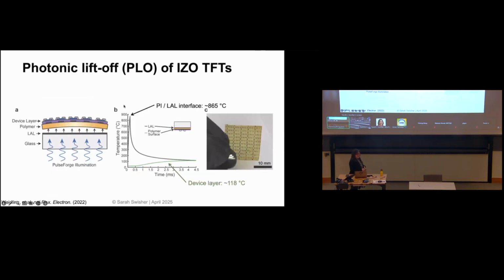So if we look at this lift-off device, what we see is that here's the temperature right at that interface. And if you look as a function of time, it rapidly drops, and here's the device layer heating up a little bit on the back side, and it reaches about 118, 120 degrees, and that's it. Okay, so this is a photo of an array of transistors. These are 60 micron channel lengths and about 500 micron channel widths on these devices.